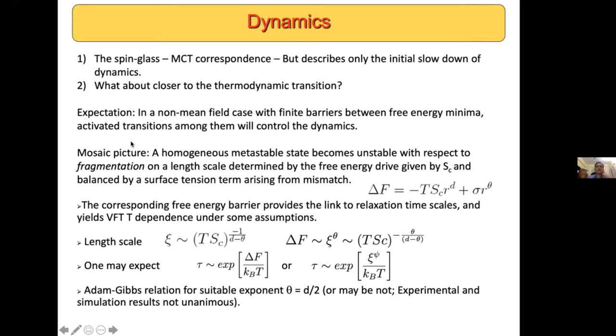From what I've already said, the expectation, now talking from the perspective of the spin glass models, is that somehow if one were thinking about a non-mean field case, the barriers between these free energy minima would be finite, and otherwise in the mean field case, these are long-lived states, and activated transitions among them will control the dynamics. So this kind of thinking led to something called the mosaic picture, where a homogeneous metastable state becomes unstable with respect to fragmentation on a length scale determined by the free energy drive that is given by the configurational entropy and balanced by the surface tension term that would arise from the mismatch between a new state that you might go to versus what already exists.